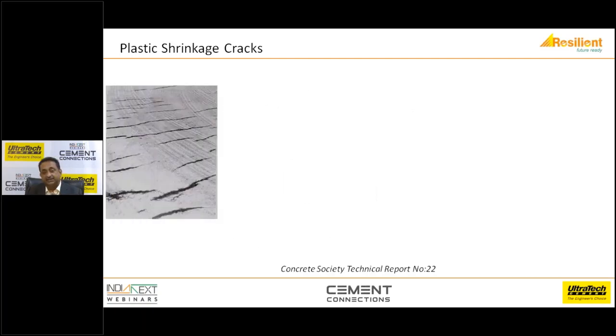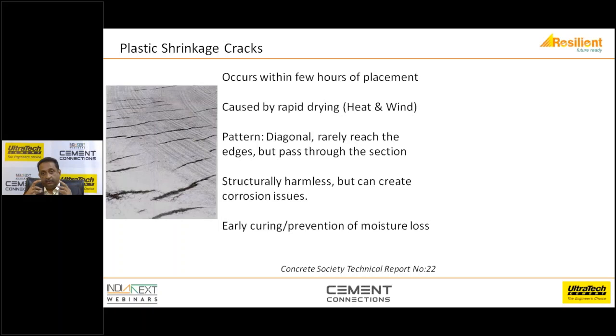Plastic shrinkage cracks are the most common cracks encountered, and they look like this, what you can see on the screen. These are random cracks, and the way you can identify this crack is that it seldom goes to the edge. Unlike what many of you think, a plastic shrinkage crack goes through and through. So if you pour curing water at the top, you can see the water leaking at the bottom of the slab. Structurally, they are harmless, but they can create quite a lot of durability issues because you are allowing a crack to happen in your system, which is not a desired thing.